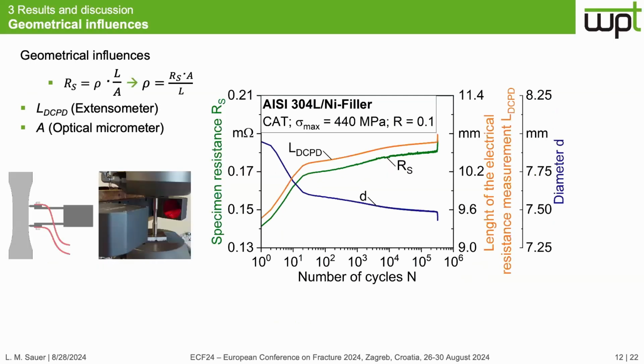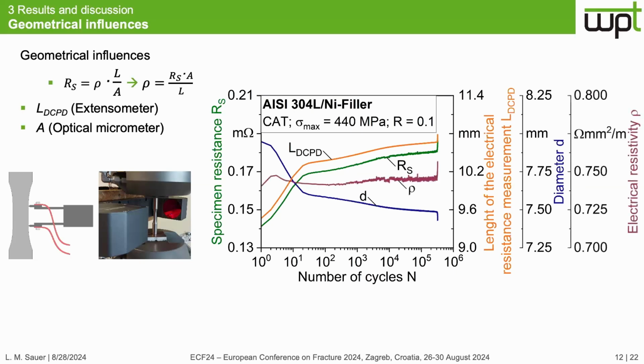And after this, the influence of geometry was compensated by determining the electrical resistivity, and therefore the length of the electrical resistance measurement was measured with an extensometer and the cross-section with the optical micrometer. And in contrast to the electrical resistance, the electrical resistivity doesn't show a significant increase. Therefore, the increase of the electrical resistance comes through the geometry.